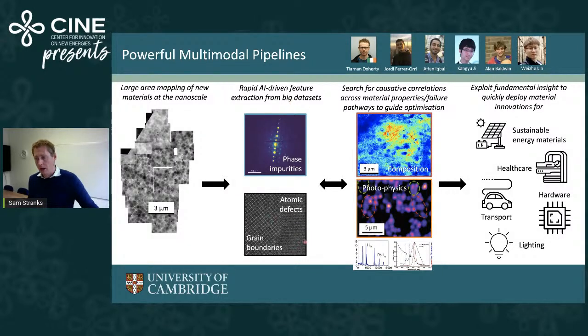We're also pushing to do that at very high resolution, with high-resolution TEM as well. And then connecting this with other properties, compositional properties, and photophysics properties as well, to really understand what are the things that cause material failure, what cause degradation, what cause performance losses, to really guide the deposition of these semiconductor materials. And the idea is to apply that now to many different materials beyond just PV, and look at these for lighting materials as well, and transistors.